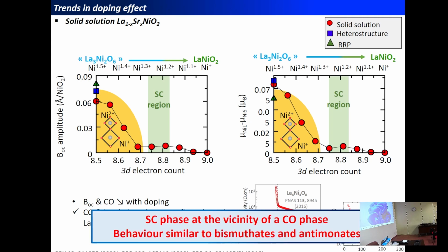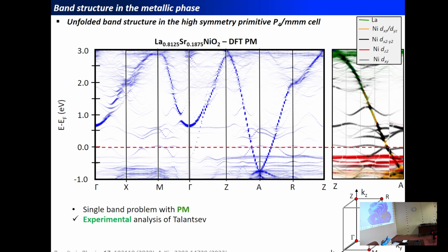And therefore, in these compounds, superconductivity is in the vicinity of a charge-ordered phase, and it appears to be very similar to what we observed in the bismutate. So now we can look at the band structure in the compound, now in the superconducting region, which is estimated to appear for this solid solution.